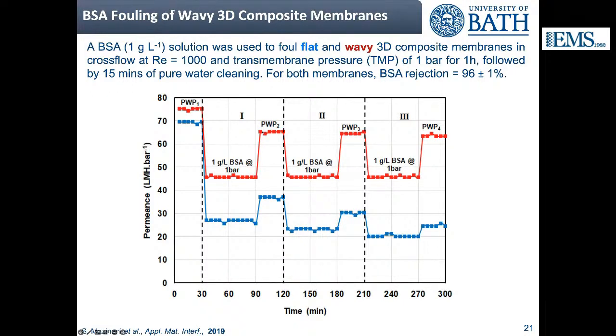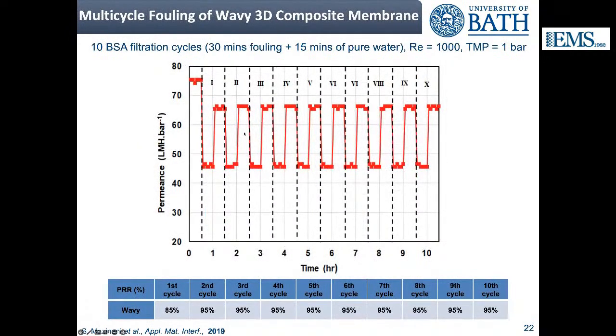Then we switch to pure water permeance. And you can see that, again, with the wavy membrane, there's significant recovery, whereas with the flat membrane, you go almost towards no permeance. You can see, quite interestingly, that the recovery of pure water permeance between the fourth, third, and second cycle is quite constant once you lost a little bit after the first cycle. We actually performed the test for 10 cycles, and you can see that after you have a loss in the first cycle, you have pretty much constant performance for 10 fouling cycles. BSA, pure water cleaning, BSA, pure water cleaning, etc.